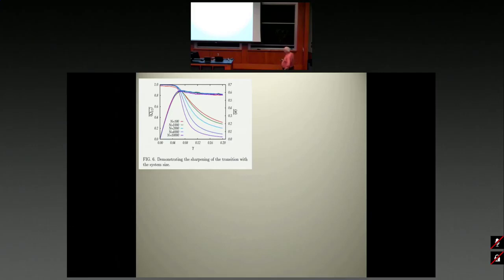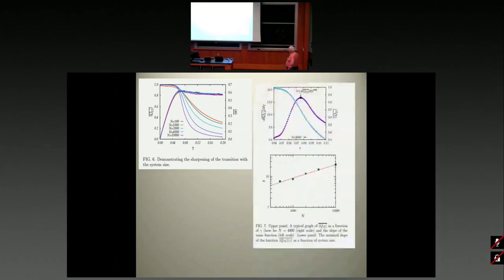For example, you can do this quantitatively. You look at the maximum of the slope. So you look at each one of these, you take the derivative, you find the maximum of the derivative, you call it S. Now you plot S as a function of n, and you see that it's a power law that is increasing. That is to say, this is very likely to go to infinite slope at the thermodynamic limit.